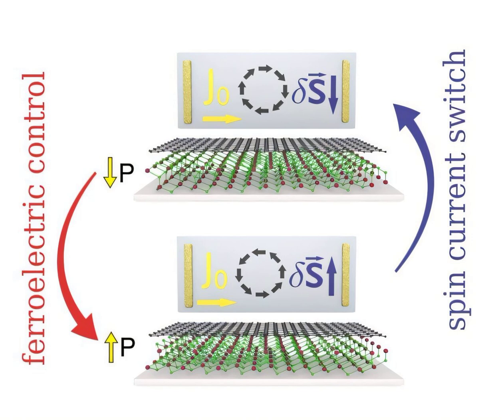Electrical control of spin currents in graphene via ferroelectric switching. A European research collaboration has demonstrated a novel method for controlling spin currents in graphene using a ferroelectric monolayer of indium selenide, In2Se3. This approach, validated through first principles and tight binding simulations, reveals that switching the polarization of In2Se3 can reverse the direction of spin currents in graphene, effectively creating an electrical spin switch. The discovery marks a significant step toward energy-efficient, non-volatile spintronic devices that do not rely on magnetic fields.